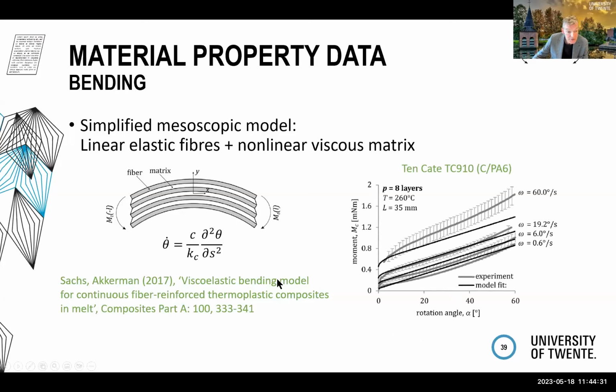If we use this kind of model and evaluate it by means of the bending moment versus the rotation angle, we get these black curves, which reasonably represent what we're measuring, apart from an increase in apparent stiffness at the higher rates. That's not included in this particular model. So again, there's room for improvement. And of course, this being very different from the classical elastic bending, this will also require a specific shell formulation to account for this.